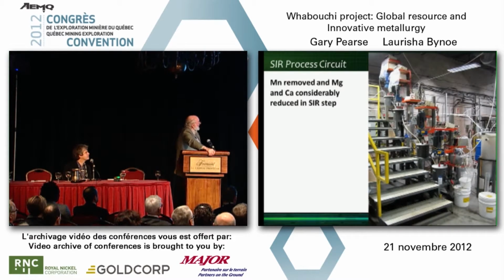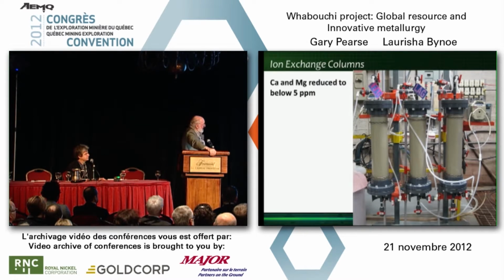And this is, we have manganese has been removed in the secondary process. The last bit of manganese is removed, and the magnesium and calcium considerably reduced down to below 200 parts per million in the lithium sulfate solution. Here's the IX columns, ion exchange. These units, you pass the solution through a resin in the IX solutions, and this selectively takes out calcium and magnesium. And depending on what we call the number of bed volumes, we've done the experimentation to know how many bed volumes are necessary to remove it down to below the 5 parts per million.